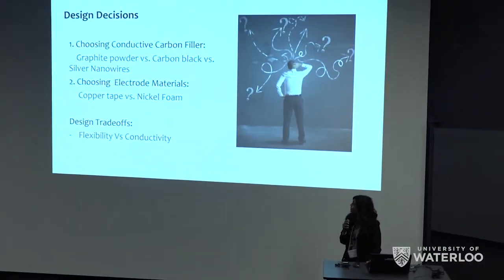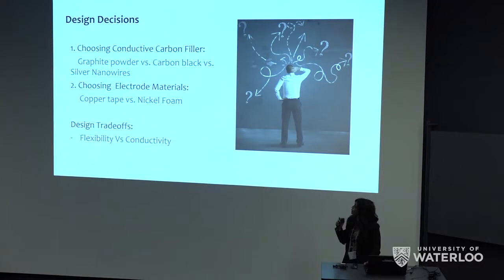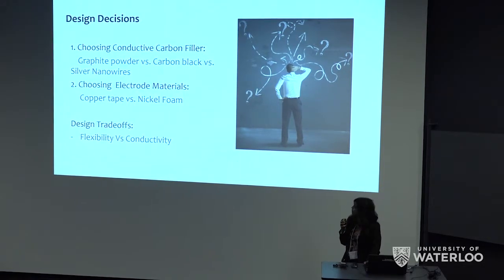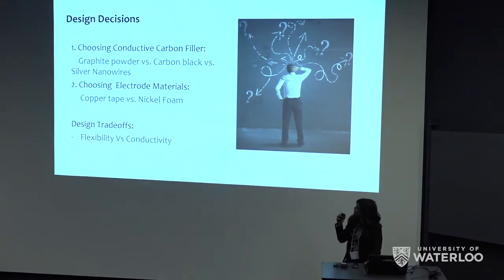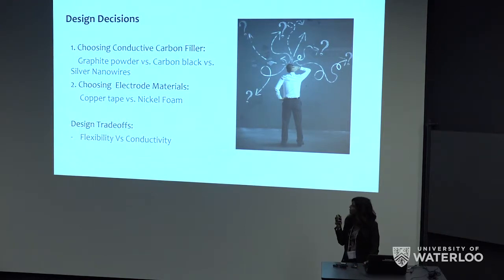At various stages, we faced some design decisions. The very first one was choosing a conductive carbon filler. We explored graphite powder, carbon black, and silver nanowires before finally settling on graphite powder as our conductive element. The second decision was choosing an electrode material. Copper tape and nickel foam were explored. We finally settled on copper tape given its ease of availability and relative inexpensiveness as compared to nickel foam.